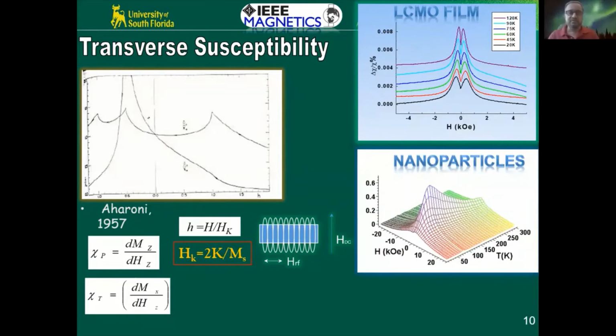We've done a lot of work on many different particles. These are maghemite nanoparticles. It's not on there, but I can tell you these are gamma Fe2O3 maghemite nanoparticles, roughly about 15 nanometers. Because we do this transverse susceptibility experiment in a PPMS, we can not only change the field, we can change the temperature. So we can track this whole thing as you go from the superparamagnetic regime to the blocked regime at low temperatures. We can completely analyze the magnetization dynamics, RF at high frequency, basically over the entire H-T plane. And that's the power of this experiment.